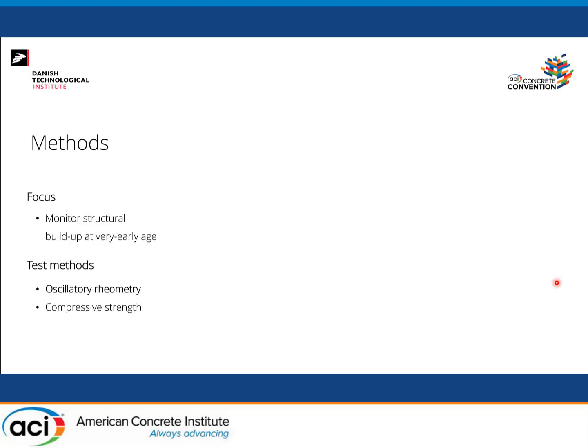So how did we map this evolution of structural buildup at very early age? And that becomes the tricky part. We're using oscillatory rheometry. And then later, for the evolution of strength, there were compressive strength tests just to guarantee against some eventual shortcomings that could come from using pure calcium aluminate cement as a slurry. So I'll come to details in the coming slides.